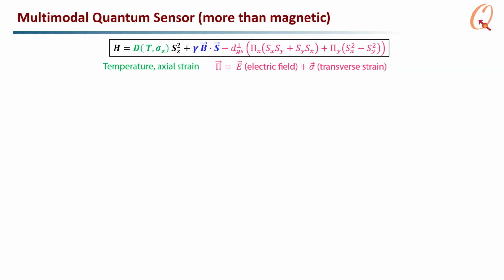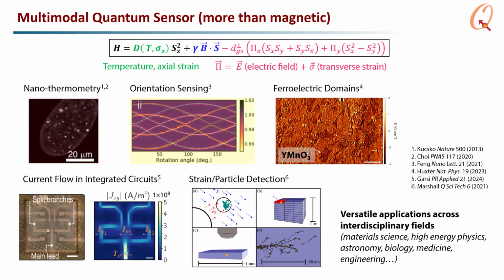Okay, so actually I kind of sold the NV center short. It's actually more than just a magnetic field sensor. So the full Hamiltonian actually depends on a whole number of things, including temperature, axial and transverse strain, as well as electric fields. So this has motivated a tremendous number of applications from nanothermometry, orientation sensing. You see there's a dot product on the magnetic field. So if you have a static field and then you change the orientation of the NV center, you can pick that out from the resonances. As well as imaging ferroelectric domains in yttrium manganese oxide and current flow in circuits, and even to detect weakly interacting massive particles that go through maybe a diamond detector, although you would need to image the strain as it kicks out atoms from a diamond detector. So you would need a lot of diamond for this to have any cross section, but it's at least been proposed.